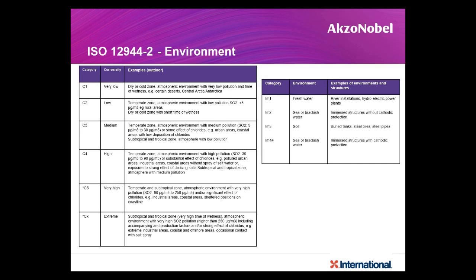C4 is high. For example, when you go closer towards any industrial area, any power plant, any refinery, that place is very highly polluted, is it not? Sulfur dioxide from stacks, nitrous oxide, equipment, material movement, those are very highly polluting areas. When you expose yourself to pollution, the rate of corrosion increases. Such locations are called C4 environment. C5 is atmosphere with very high level of pollution, significant exposure to chlorides: industrial areas, coastal areas, sheltered positions on the coastline. For example, the coastline of Mangalore, Mumbai, Colombo, Chennai, Visakhapatnam, Gujarat, these are C5 environment.